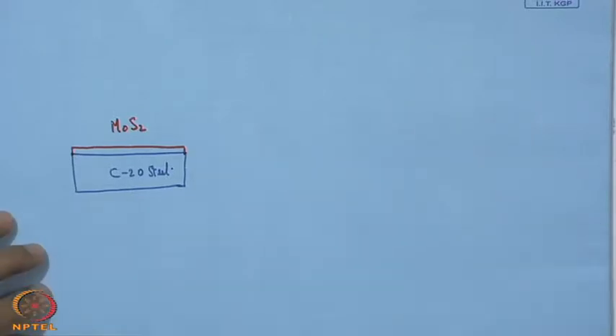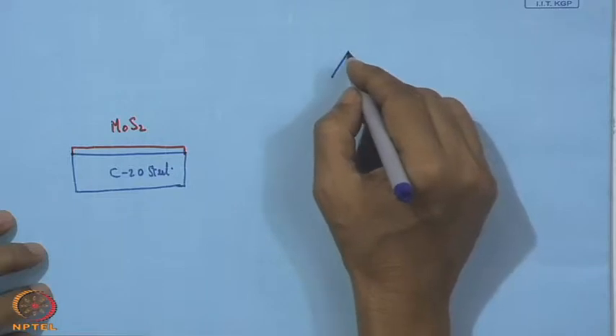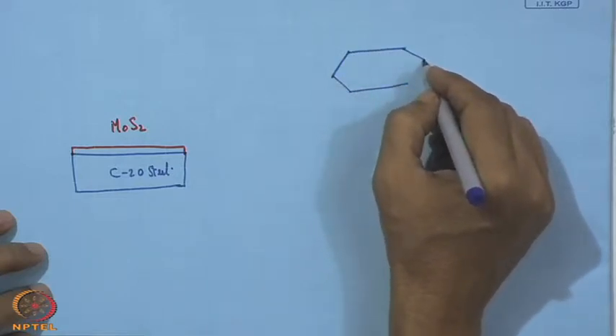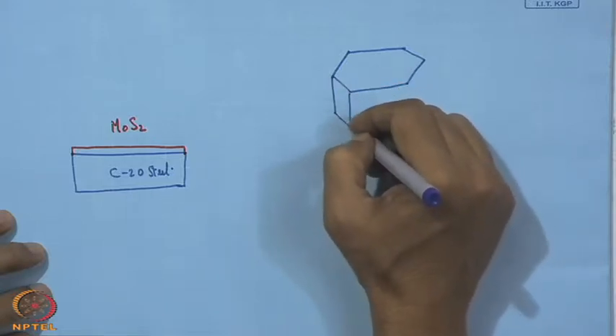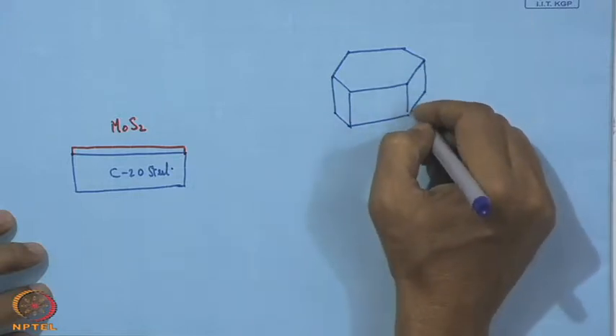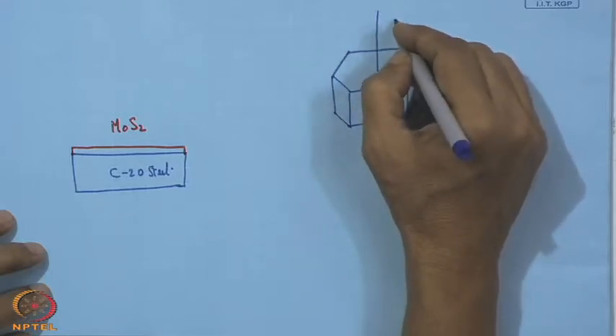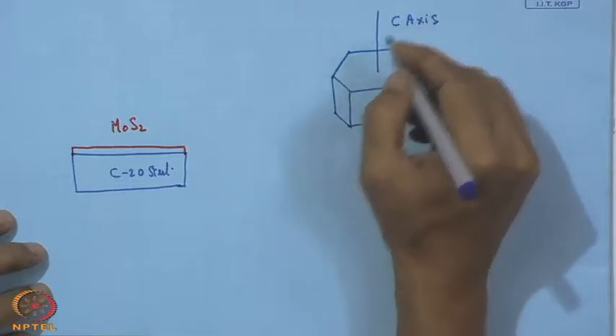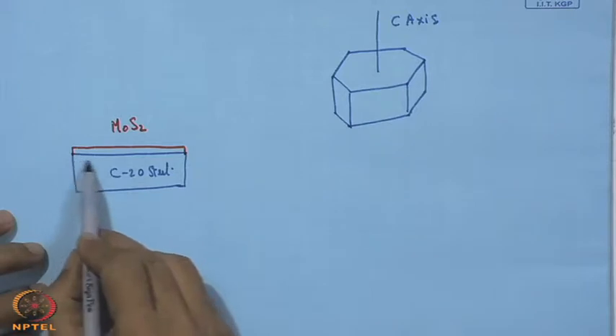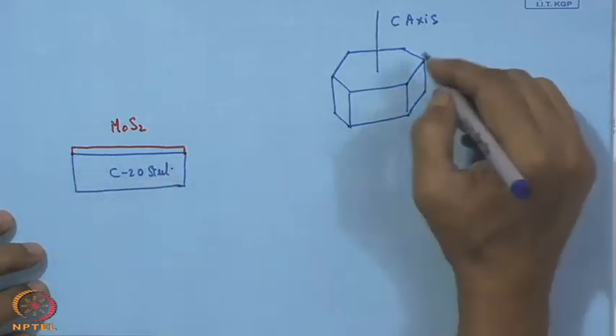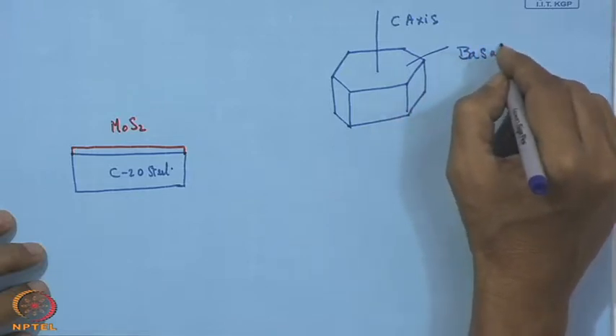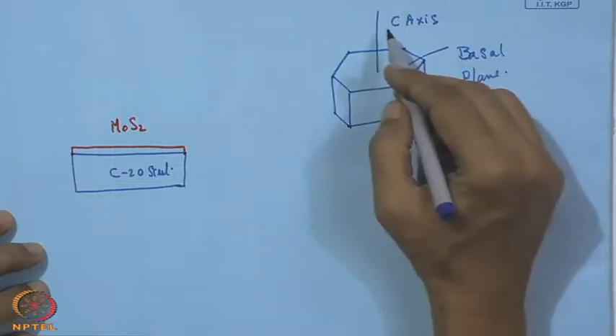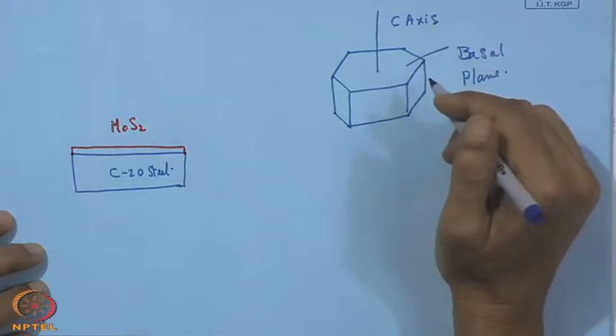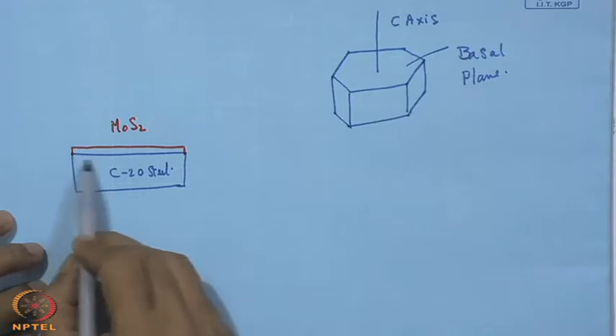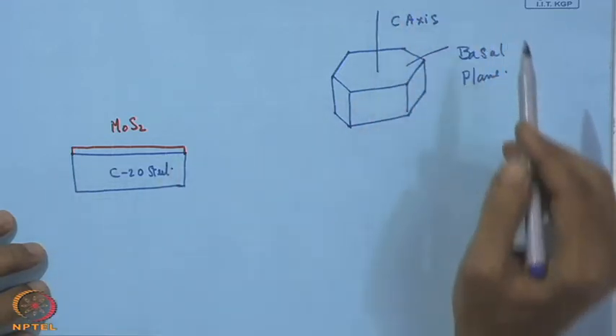So, let us look at what it means if we put this hexagon like this. This is one way of showing. So, that means here this axis, what we call the C axis, is perpendicular to the surface of the substrate. So, this is one situation. So, this C axis is perpendicular to the substrate, or we call it the basal plane. So, here two things we must take notice of. One is that the basal plane is parallel to the substrate surface, and obviously the C axis is perpendicular, but we can have